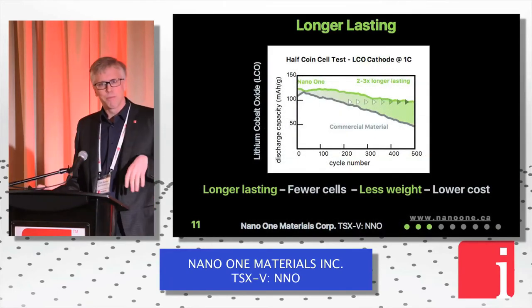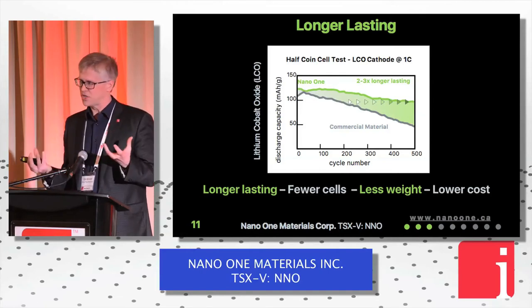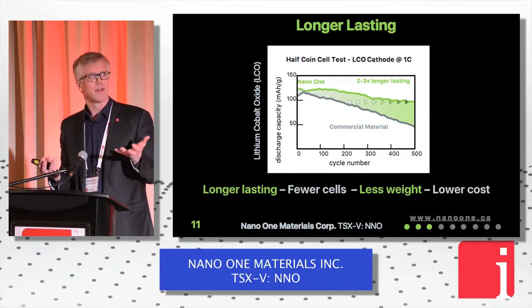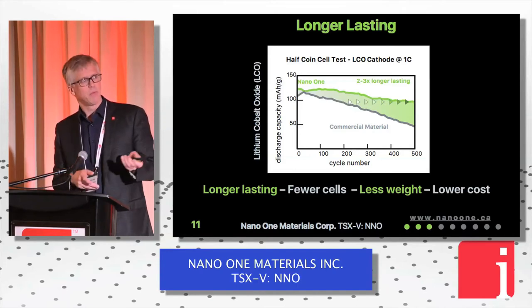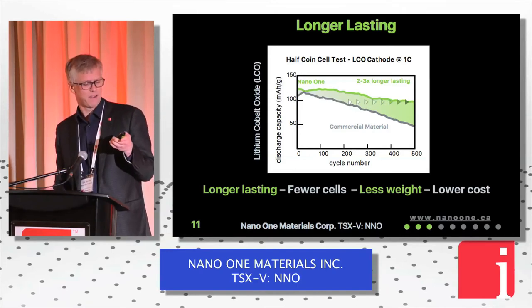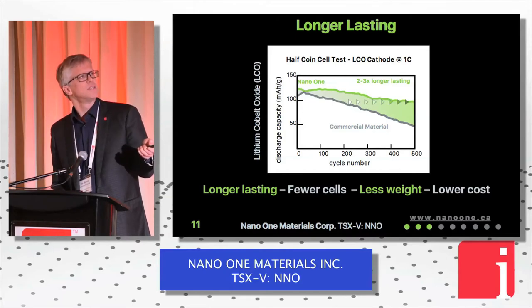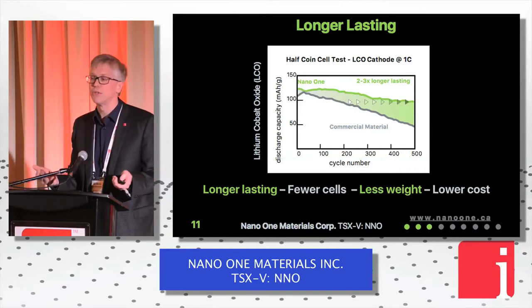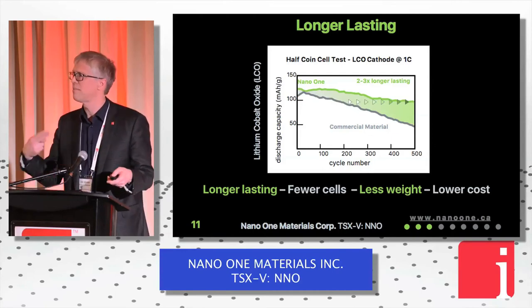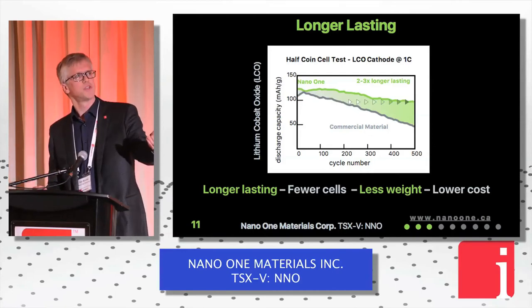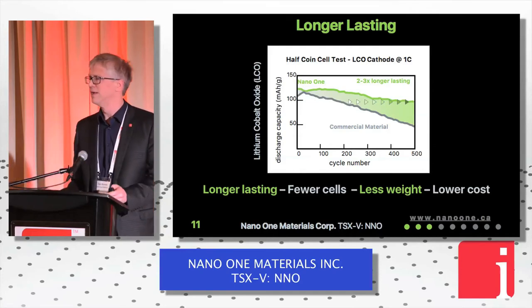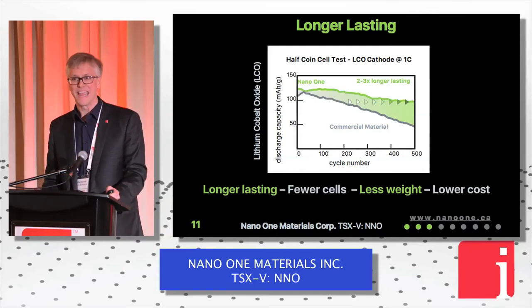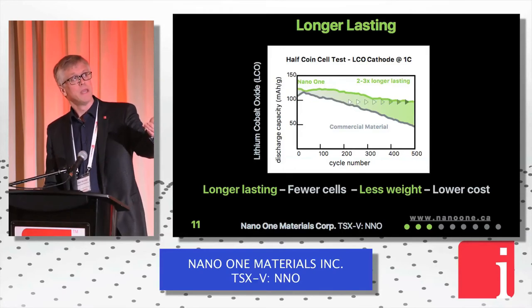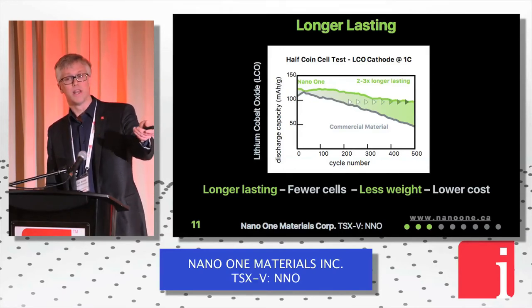Some of the other value propositions are on the battery side of things. So when we take our material and we form a lithium ion battery with it, we'll get longer lasting materials. In this particular graph, the green line represents Nano One's cathode material in a battery, and the gray line is a commercial material made into exactly the same battery. We've tested these over many, many cycles. About the life cycle of your cell phone, 500 cycles is about what your battery starts to really decay on your phone. That's about 2 years worth of play. And you can see that the gray line degrades much faster, the green line less so.